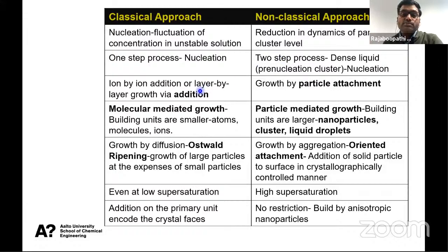Here the growth is by ion addition. In the case of a molecular crystal, it is molecule by molecule addition. Here it is particle attachment in non-classical growth. We can say the classical approach is molecular mediated growth. The non-classical approach is particle mediated growth. Sometimes even a single crystal looks like it has an unsmooth surface. The outer surface may not be smooth like a single crystal. It is actually happening due to Ostwald ripening. I will explain what Ostwald ripening is later.